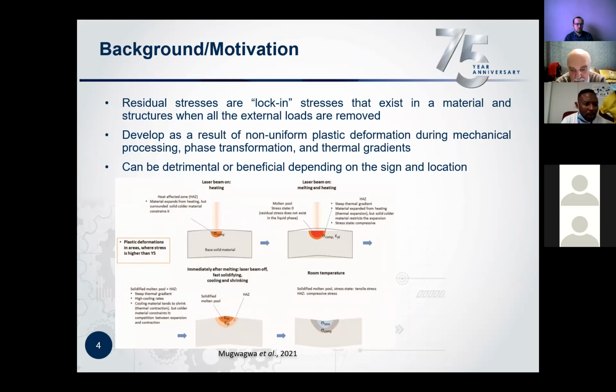Here is a schematic diagram explaining how the stresses develop in additive manufacturing. The laser heats up the powder and your base plate. The temperature rises and you get expansion. As the temperature rises beyond the melting point, the powder melts and you form the molten pool, but in the liquid state there are no stresses. Around the heat affected zone, you start to get some thermal expansion, but the material is not expanding as rapidly as it should because the cooler material around it is constraining it from expanding. When the laser is switched off, you get contraction. Again, because of thermal gradients, the cooler material constrains the hotter material from contracting at the faster rate, and you eventually end up with tensile stresses on the surface.